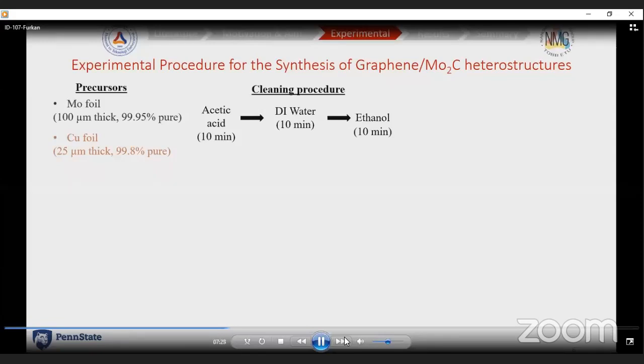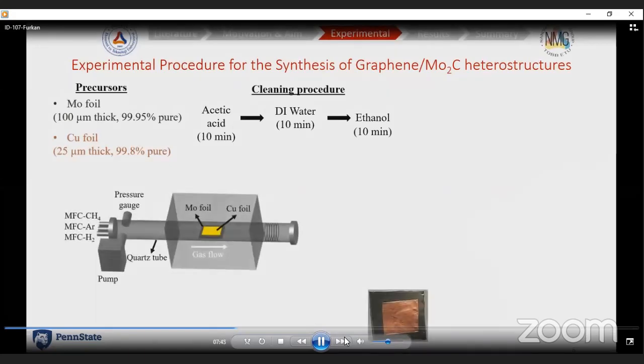So similar to the literature, we used molybdenum and copper foils as precursors, and we first cleaned them in acetic acid, DI water, and ethanol sequentially for 10 minutes each. And after that, the copper foil was placed on top of the molybdenum foil, and then it was introduced into the furnace. And the system was heated to 1090 degrees C under hydrogen atmosphere.